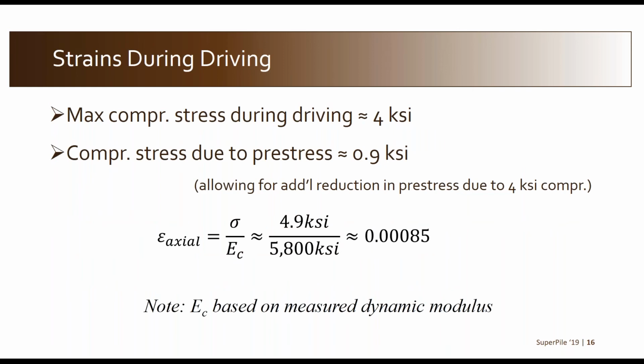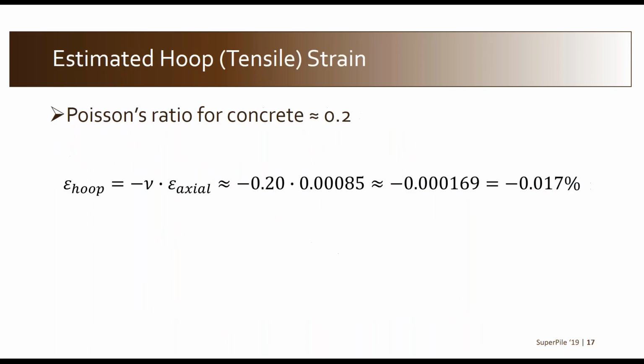Okay, now we're going to go through a short exercise to relate that to hoop strain. So the maximum compressive stress during driving of about 4 KSI is additive with the pre-stressing force because the pre-stressing is trying to compress the whole pile. So we can calculate strain in the axial direction using the measured dynamic modulus. And then we can calculate a hoop strain from that axial strain just using the simple Poisson's ratio relationship. So for concrete, the Poisson's ratio is about 0.2, and we would calculate there a tensile strain in the hoop direction of about 0.017%,